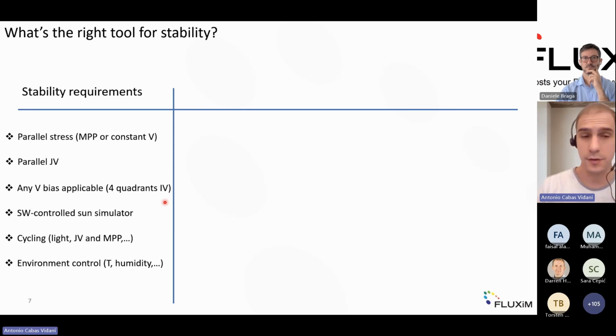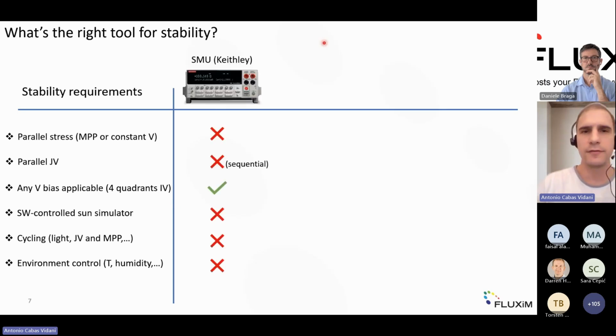You want the sun simulator to be software controlled so that you can automate and coordinate the measurement, the bias, so to speak, with the illumination. You want to cycle your type of measurements, and you also want to control the environment if you want to get, for instance, controlled humidity or inert atmosphere. And what we have typically in a laboratory is an SMU, like a Keithley, for instance. Here you definitely don't satisfy many of the requirements. You have very good high quality JV measurements, but only for one sample at a time.